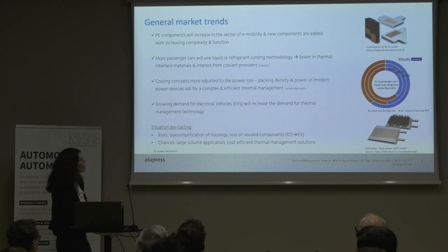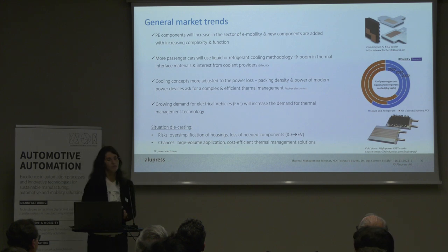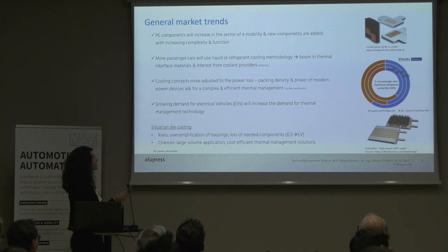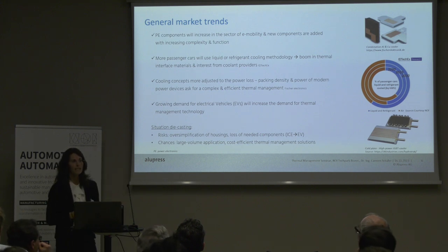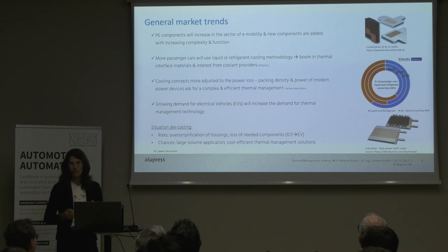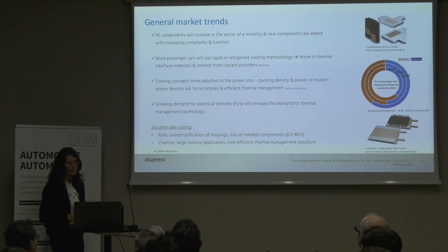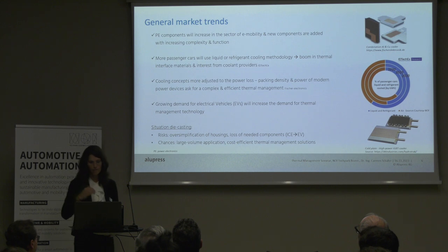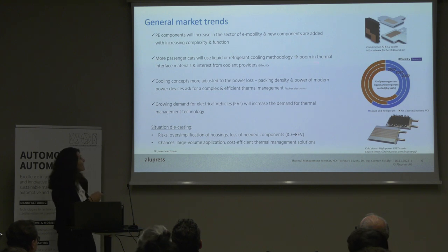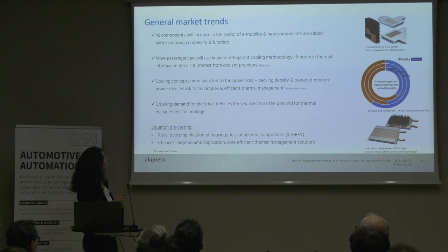And when we look at this graph, we have more and more, exactly the example of what we heard before, liquid cooling. Traditionally, we had lots of heat sinks with air cooling. This is not sufficient anymore, especially since the silicon carbide chips are coming, with temperatures rising to 165 peak. That means we need to remove more energy on a smaller dissipation area. That means changes in packing density, changes in dimensions, but also finding efficient thermal management solutions.